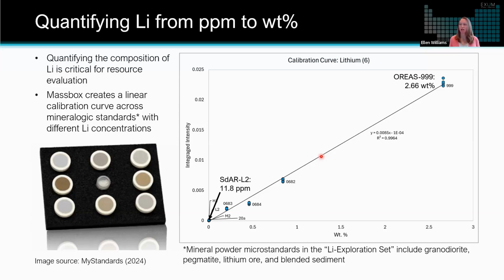Having multiple points along a calibration curve is ideal when we have some sort of unknown material and an unknown amount of lithium that could span multiple orders of magnitude. But I will say, we don't always need 8 reference materials in order to get quantitative data. We can do single point calibrations as well. So if you know the type of mineralogy that you've got and you have an unknown with that same mineralogy, it can be very straightforward to just use a single matrix match reference material and do a single point calibration. But of course, we know that that's just not always the case when it comes to exploration. We may have no idea what rock type we're in, and so having a calibration curve like this allows us to span a wide concentration.